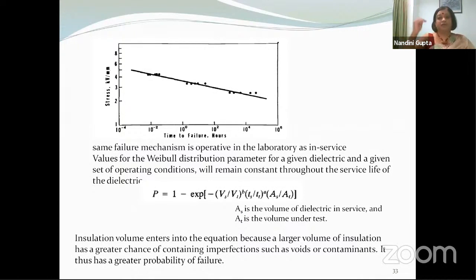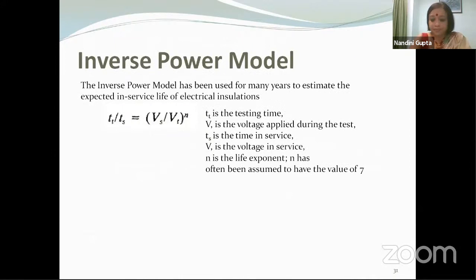As you keep on increasing your voltage level, for example, I already mentioned the case of traps filled with charge accumulation. Then, for example, partial discharges. It might be that at a very high level, certain partial discharges or certain corona, which will not happen under operating conditions, begin to happen. So it is very important to remember that the failure mechanism is true to the service conditions.